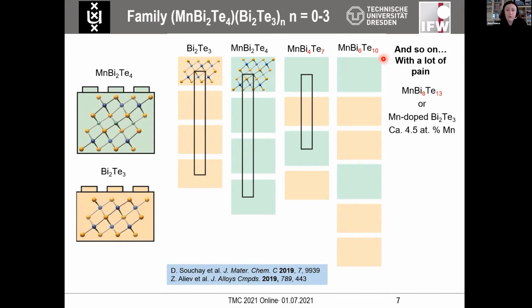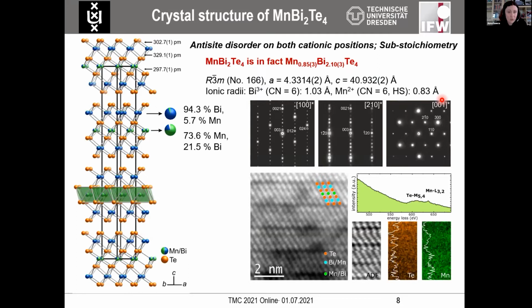Therefore, when you get into the area of 1-6-10 and 1-8-13 compositions with 2 or 3 quintuple layers between the septuple ones, you're basically fighting against small fluctuations of temperature and kinetics. And despite all the tricks, you may end up with different compounds than you would like to. That naturally leads to some variety in the reported results on these phases, but there are even more complications that are connected to the structure of these materials.